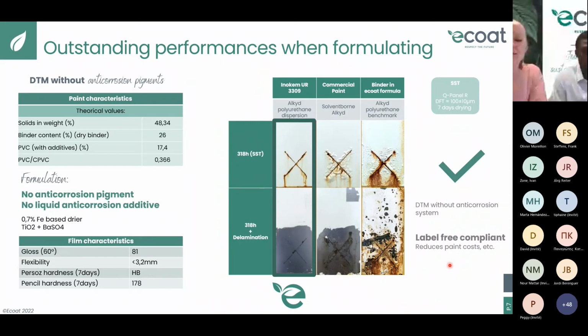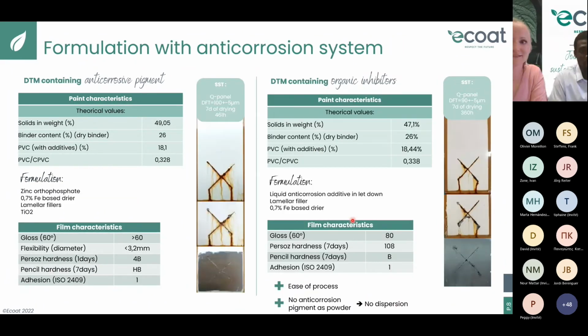But to reach higher performance, it is mandatory to have an anti-corrosion system in your formula. So now let's see what we can do with an anti-corrosion system in the formula. Here are two kinds of formula: one with anti-corrosive pigments and one with organic inhibitor. With a DTM containing anti-corrosive pigments, we can easily reach 400 hours of salt spray with good adhesion and good gloss. And here on the right side, you can see results of a formula containing a liquid organic inhibitor. This kind of additive can boost the anti-corrosive performance and ease the dispersion of